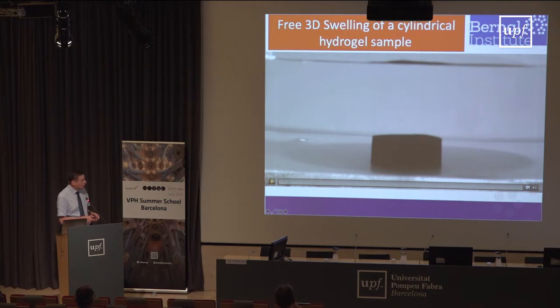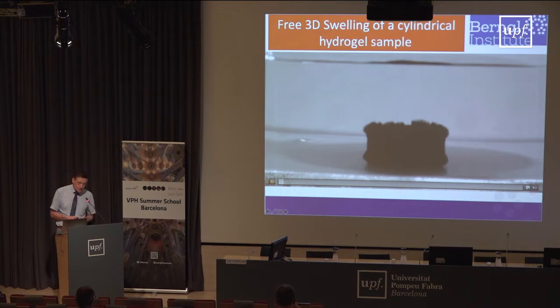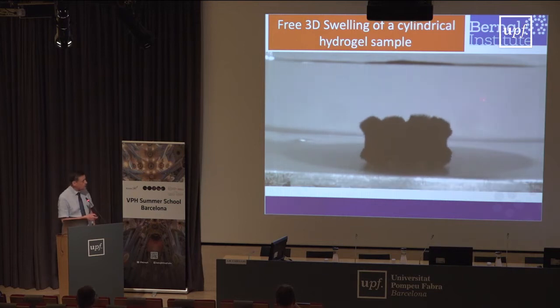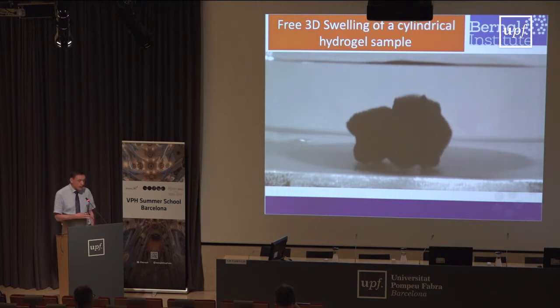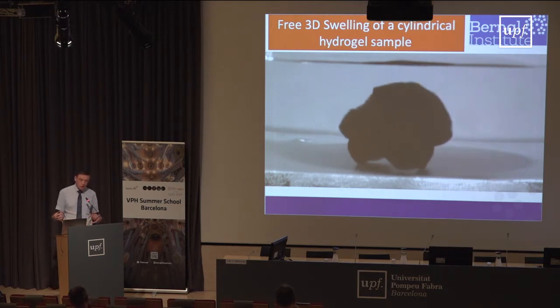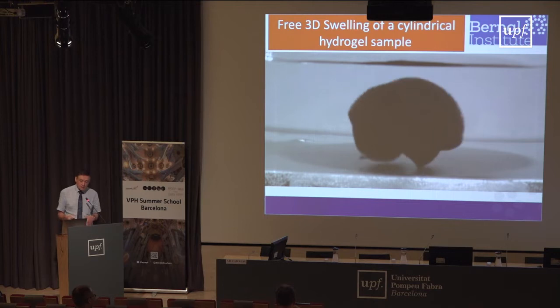a gel of a cylindrical form. And we move it from high salt concentration to low salt concentration. And then it starts swelling, but it develops surface instability, which here you can see very clearly because it starts with a cylinder. What happens, in fact, is that the outside swells first and the inside doesn't, because the water cannot reach inside. And then the kernel and the outer surface need to remain in contact with one another. And the way it does, it goes into surface instability and later into a kind of saddle shape.